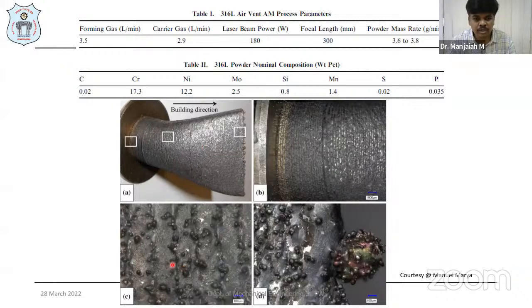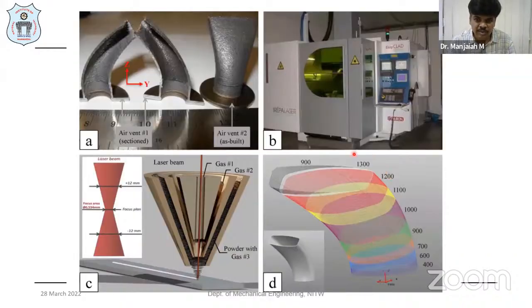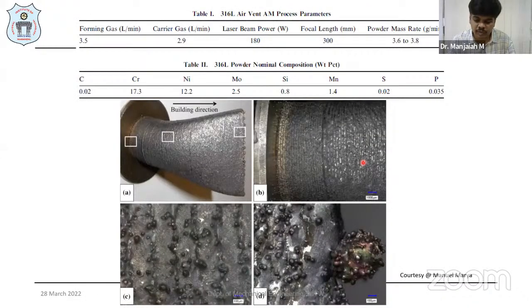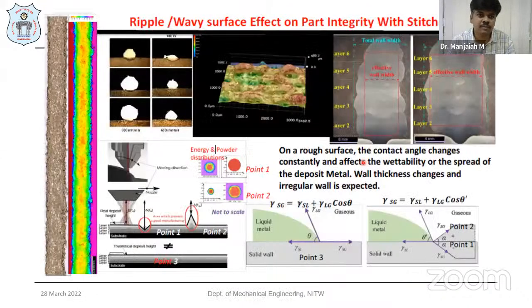You can see in the exaggerated view, there are all the unmelted powder particles which are sticking onto each of the layers. And even in the top surface, you can see this kind of balling effect because the scan speed is very, very high, 1300 scan speed. In such cases, we are going to have this kind of balling effect.